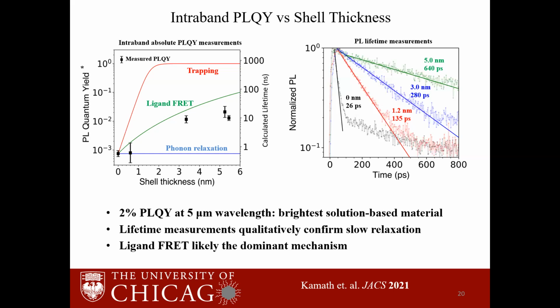Okay, so the question is, what is the reason for the discrepancy, and can we go brighter if we go to thicker shells? One thing I did not mention, this small star that we see over here: if the doping is large, then the quantum yield decreases significantly as we go to larger dopings. So there is another mechanism, which is not just the ligand FRET, but probably due to defects within the shell, which is reducing the quantum yield. So this disagreement could be because of that.